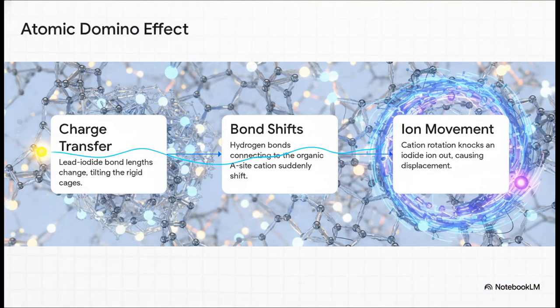By combining all these clues, researchers mapped out the exact atomic domino effect triggered by light, and it happens in 3 distinct steps. Step 1. Light hits, causing an immediate charge transfer that physically changes the length of the lead iodide bonds, which tilts those rigid cages. Step 2. Because the cage tilted, the delicate hydrogen bonds connecting the cage to the organic A-site cation inside suddenly shift. And then step 3, the organic cation, reacting to this totally new environment, violently rotates or flips. If it doesn't have a strong enough dipole to anchor things down, this rotation physically knocks an iodide ion out of its spot, causing displacement. So 1 photon of light, 3 steps, and suddenly your crystal is degrading.